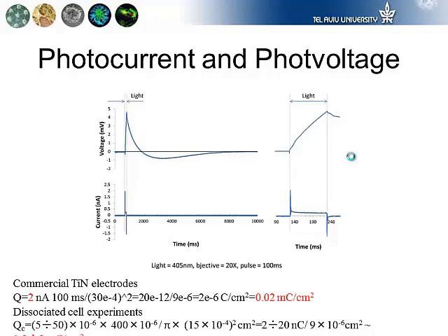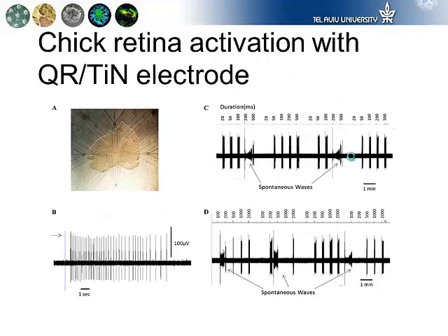And these devices can yield very nice polarization with pretty sizable voltages and also photocurrent. This is just measuring the photovoltage or the photocurrent building up on these electrodes. And again, putting a retina on, shining light, we can actually demonstrate electrical stimulation with these films.